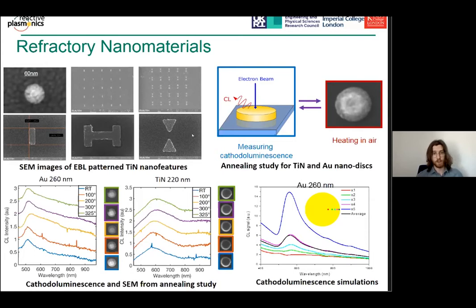Once we pattern these thin, small materials and these nano features, we're interested in understanding their temperature stability as well. So we did an annealing study and a temperature stability study using cathodoluminescence, where we measured the optical response from individual nanoparticles, annealed them, and assessed the change in the optical response and in the morphology with temperature. And we see that from 200 degrees, there are spectral changes in both gold and titanium nitride, but titanium nitride retained its shape up to 600 degrees. And we supported all of this with modeling. So we did dipole-dipole simulations of the cathodoluminescence response of these materials.